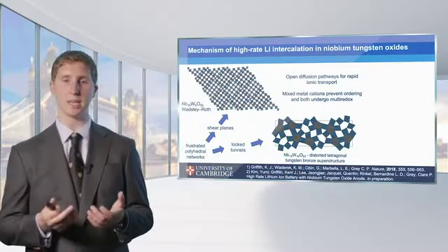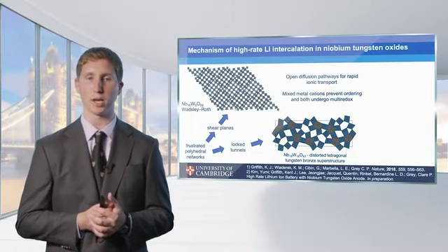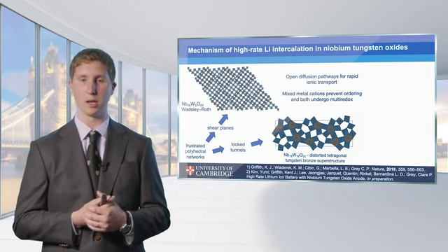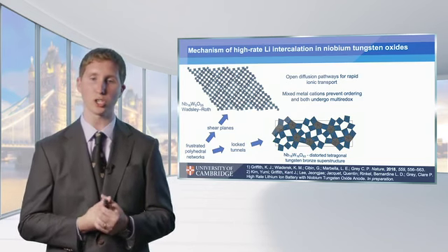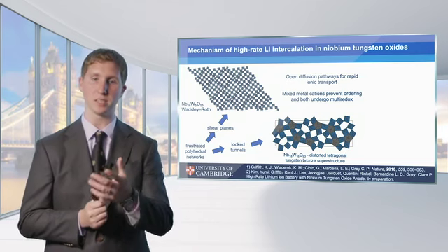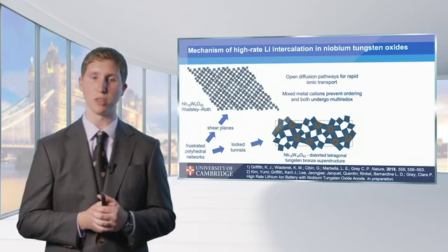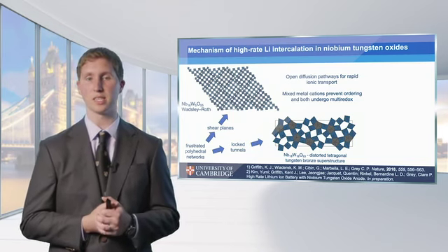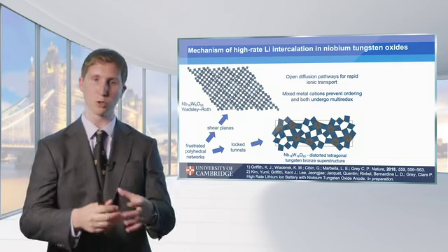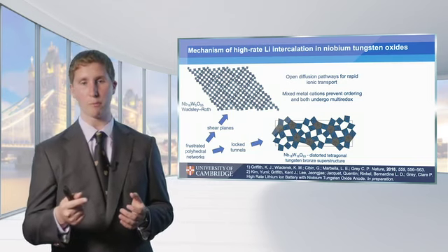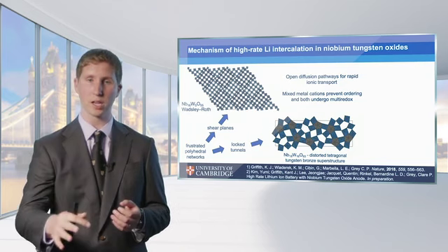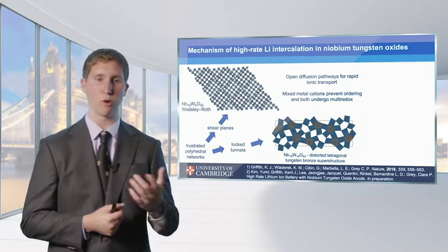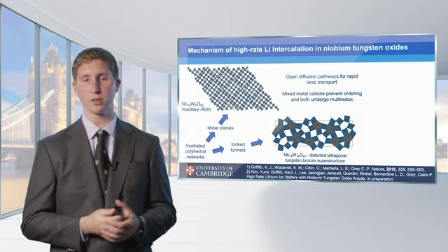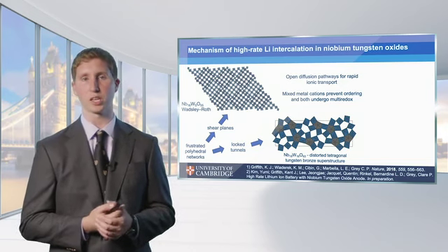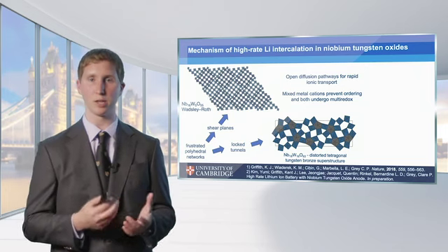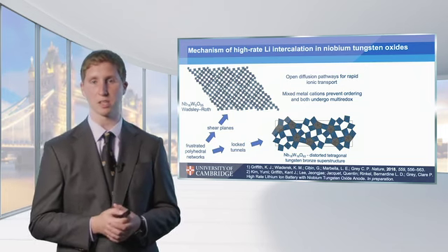So these things maintain an open diffusion pathway, something like a room and pillar network in the bronze structure, where you keep these 2-dimensional open spaces and even have some additional 3rd dimension through the empty tunnels. And then this bulk diffusion, sort of like a multi-lane highway, where lithium ions can hop between different openings in the block and go rapidly through the open structure. And then the other thing, of course, is that we have the multi-electron redox coming from both the niobium and the tungsten. So that really allows us to push how much capacity we can get out of these materials.